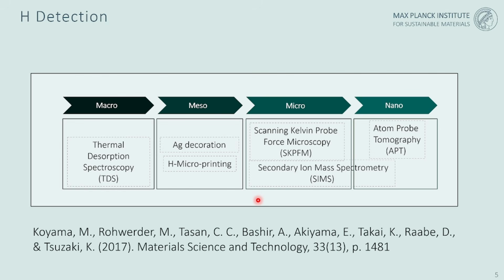When you go to a yet finer scale, you could also use scanning Kelvin probe force microscopy, which can be calibrated to a very, very high sensitivity to show you at a local scale where hydrogen is leaving the sample. And when you go to yet finer scale, you can also resort to secondary ion mass spectrometry, SIMS and nano-SIMS techniques, where you have a relatively high sensitivity, but these are now increasingly techniques where you might want to make sure that you load the material not with hydrogen but with deuterium, because in mass spectrometry the hydrogen can be easily confused with ambient hydrogen that you have in your measurement system.